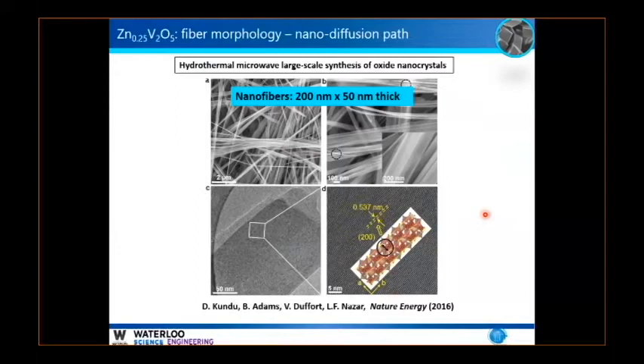So in 2016, we developed, using nanotechnology or nanoscience, these nanofibers of a zinc vanadium oxide, and we did this by some special hydrothermal technology. And the point here is that you can see these hair-like structures that are effectively 200 nanometers by 50 nanometers thick, and they're microns and microns long. So they have a higher aspect ratio even than something like linguine, for example. The thinness of these fibers allows efficient mass transport of the zinc ions through this structure, which would otherwise be limited if we were looking at micron-sized particles.